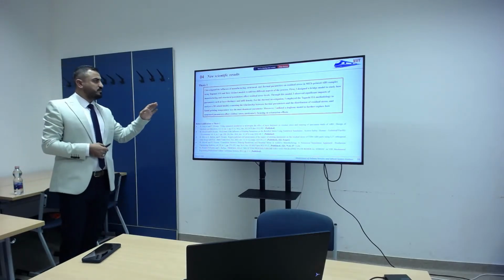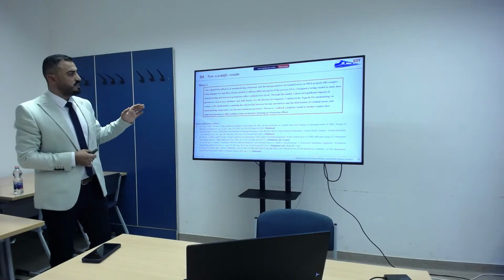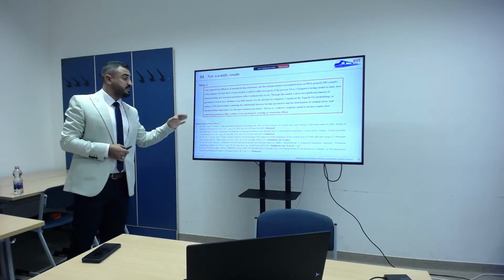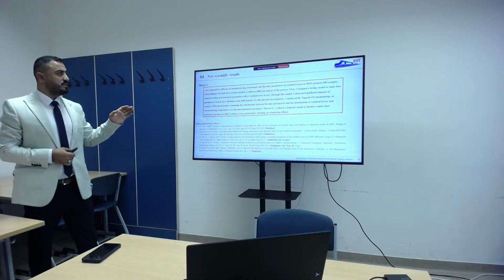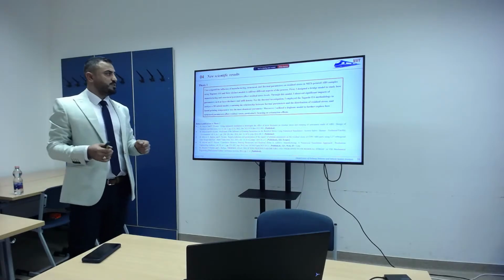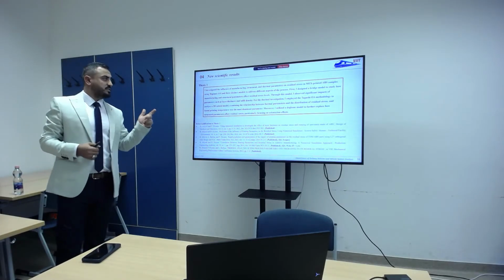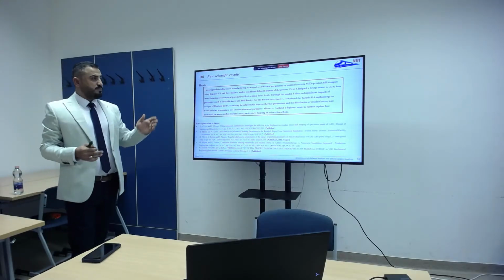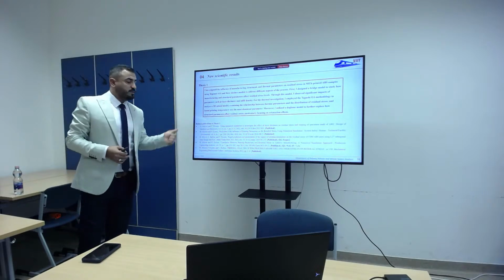So, for thesis number 1, I investigated the influence of manufacturing, structural, and thermal parameters on residual stress in material extrusion printed ABS samples, using 3 distinct models to address different aspects of the process. First, I designed a bridge model to study how manufacturing and structural parameters affect residual stress levels. Through this model, I observed a significant impact of parameters such as layer thickness and infill density.